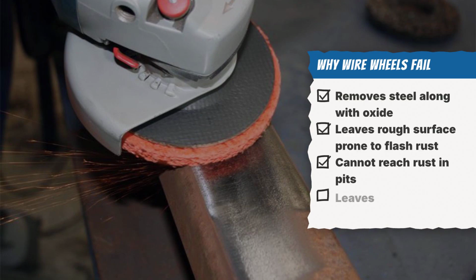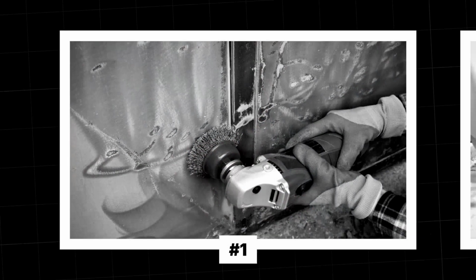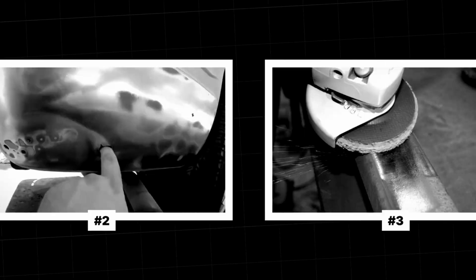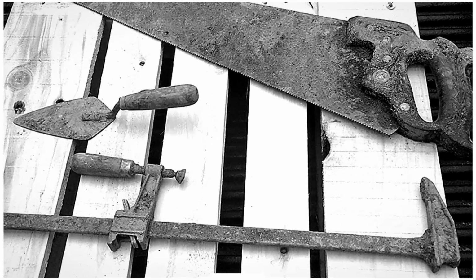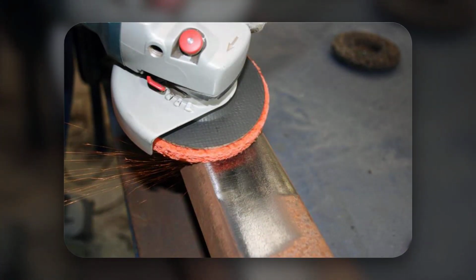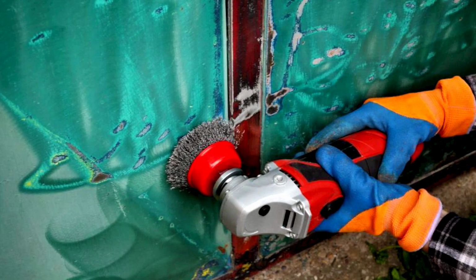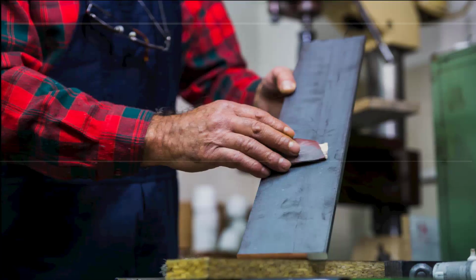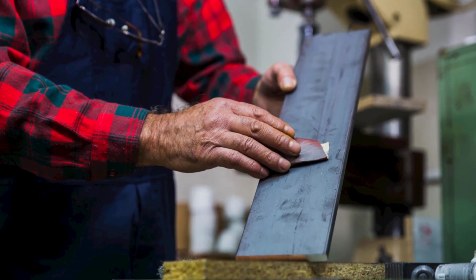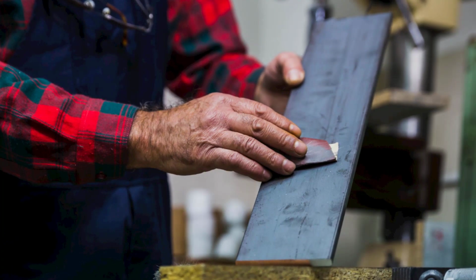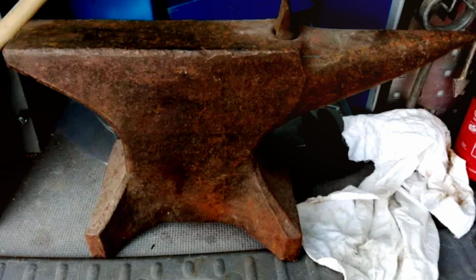Now, the things that do not work, and the exact reason each one fails. The wire wheel on a drill or an angle grinder. It looks the most professional, and it does the most damage. It removes steel along with the oxide, which on a sharpened edge or a thin pruner blade is metal you cannot get back. It leaves a rough surface that flash rusts faster than the tool did before you started. And it cannot reach into the bottom of pits, so it grinds the tops off the rust and leaves the roots of it sitting in every hollow, ready to spread outward again.